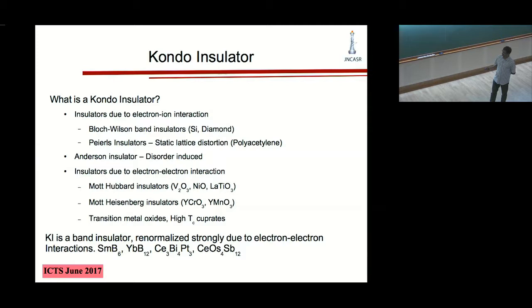Basically, they are renormalized strongly, and they are band insulators to begin with. They're renormalized strongly due to strong electron-electron interactions. So there would be a band gap, like a silicon-like band gap, in these systems if there were no electron-electron interactions. But because of these strong interactions, the gap gets strongly renormalized, and you see gaps which are of the order of millielectron volts rather than electron volts, which you see in normal semiconductors. And these are some of the examples here.